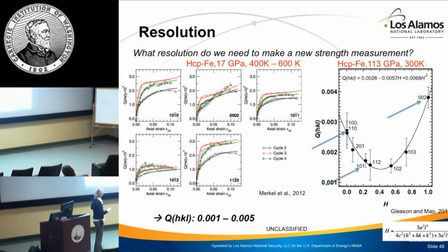So in our dynamic compression experiment, we do have a good range of lattice parameters. And that means, moreover, the sensitivity that we need to get to is down to a Q of maybe 0.001. So a fairly low value. And the current state of the art in terms of strength measurements in a static compression sense is at a combined pressure and temperature of something like 17 GPa and 400 to 600 K, something like that, okay? So we look at some of our calibrants to assess, do we have the resolution to make this measurement?